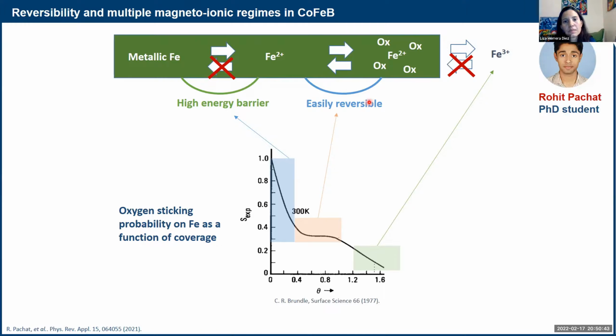What supports this assumption even more, which I haven't shown so far, is that if we take this state, this is in plane, and then we keep adding oxygen, at some point it will not be reversible anymore. We won't be able to come back to this. So we think that once again, if you overdo this, then you land on an iron 3+, and then you have the same problem as you had here. It takes a lot more energy to go from here to here. This is why, with our limited window of voltages, we cannot see this coming back to this. So this is basically what I wanted to show you here.